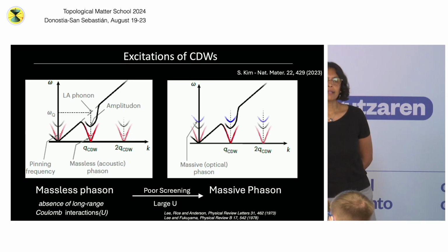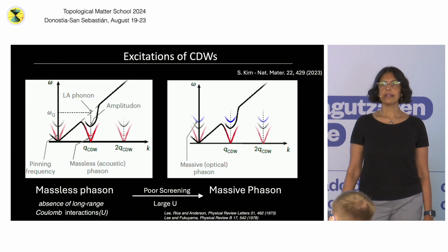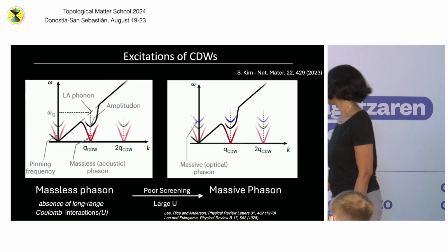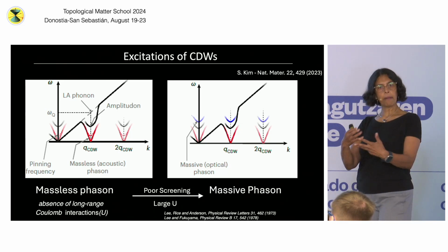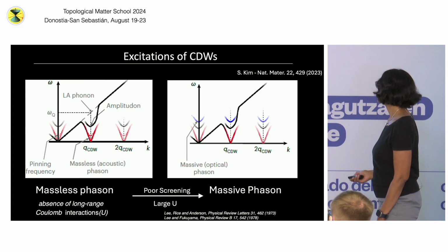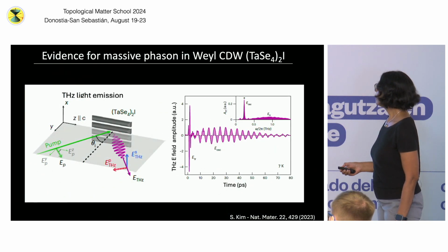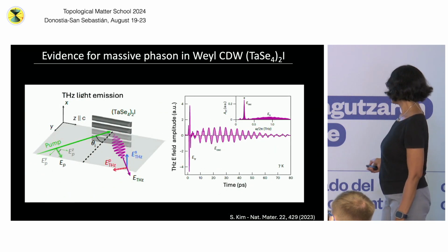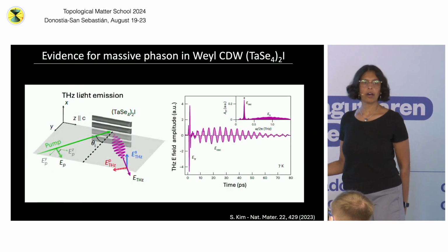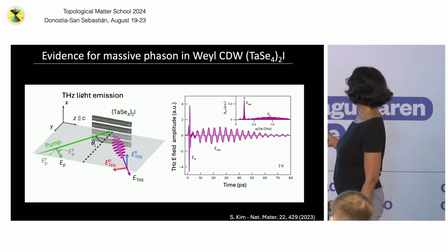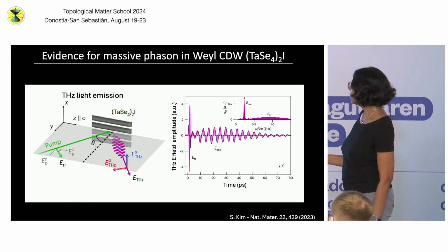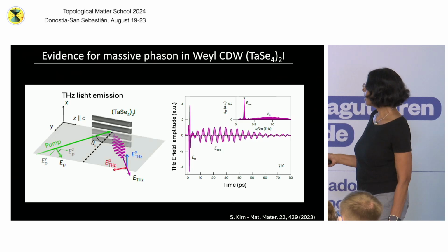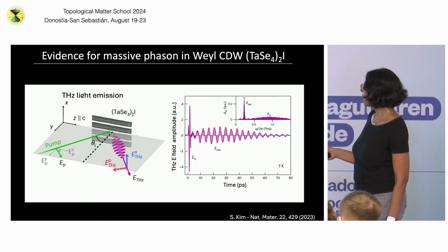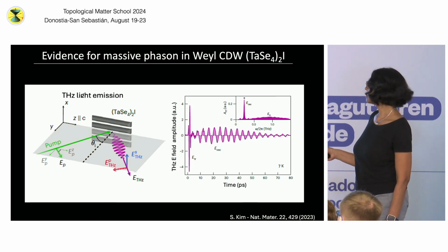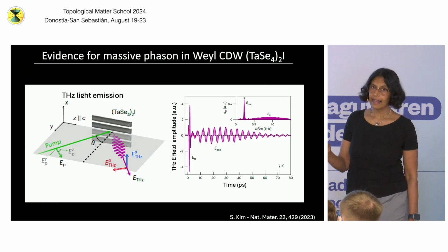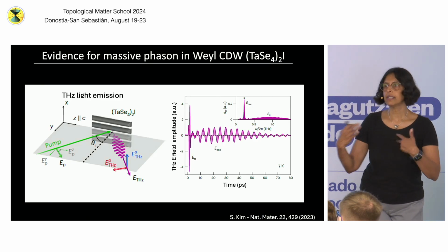And the mechanism by which this happens is, like I said, similar to the Anderson-Higgs mechanism for giving mass to massless particles. So this was first observed just last year by my colleague Fahad Mahmood in the same sample I'm talking about. What they did was they applied light, optical pulses to a sample, and in their measurement, they measured the emitted terahertz.